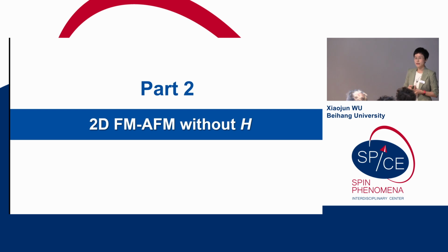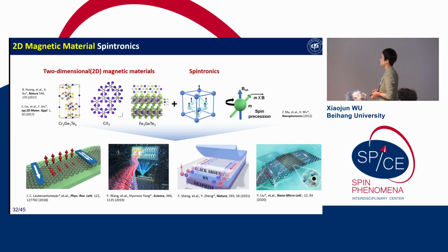And the other thing is that for this one, we do not need the field, and recently we demonstrated another work on whether we can use this method for 2D magnetic materials. So why 2D magnetic materials? Because 2D magnetic materials have a lot of potential applications in spintronics. But the main point here is that when we thin these magnetic materials, due to thermal fluctuation, they cannot keep long-range magnetism at room temperature.